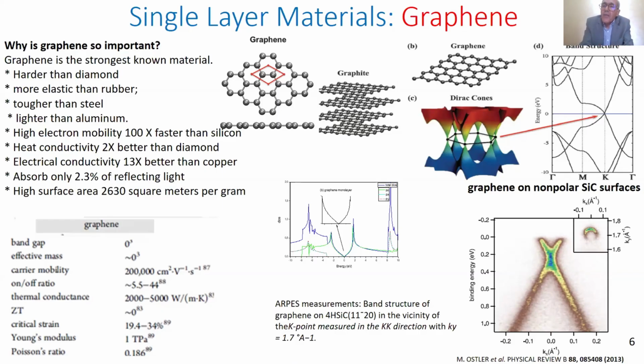The theoretical study shows that this material exhibits a Dirac cone, and also linear dispersion energy and gapless, and this result obtained theoretically has also been observed experimentally by the linear behavior by measurement of ARPES. So this material is very important, and it launched the study of 2D materials because of its unique properties.